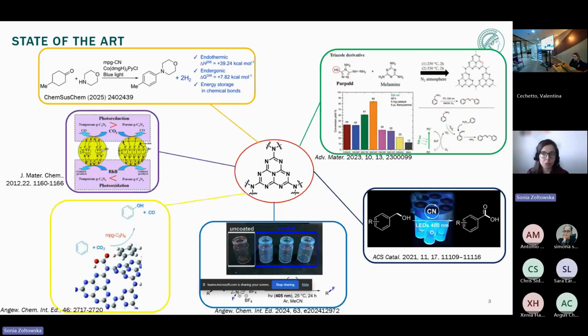The field is big because within more than 20 years, carbon nitride has been applied for very different types of photocatalytic transformations, from organic photoredox reactions like here amination reactions, some oxidation reactions in bulk form, but also, as you can see in those two works, we were able to use thin film of carbon nitride coated directly on the vials to make simple oxidation reactions and also fluorination reactions. But carbon nitride in bulk form was also proved to work for CO2 reduction in its mesoporous form and also in the nanoporous graphitic carbon nitride form.